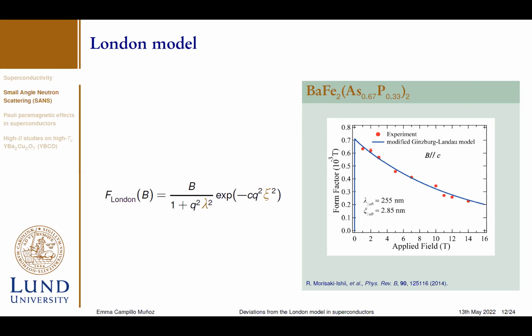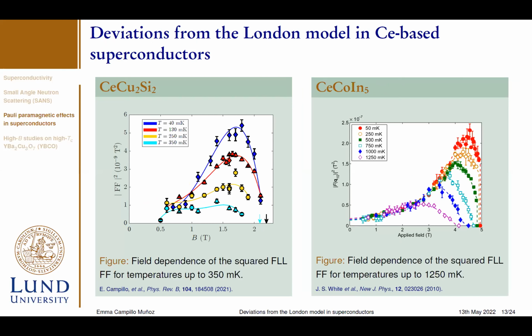But what happens if we find out that the form factor is not behaving as we expect? We measured the form factor of CeCu2Si2 at several temperatures, applying different magnetic fields. Surprisingly, we found that the form factor is actually increasing instead of decreasing when approaching the upper critical field. This is rather shocking, but we already found this kind of behavior in another well-known cerium-based superconductor, CeCoIn5, and it has been attributed to Pauli paramagnetic effects.